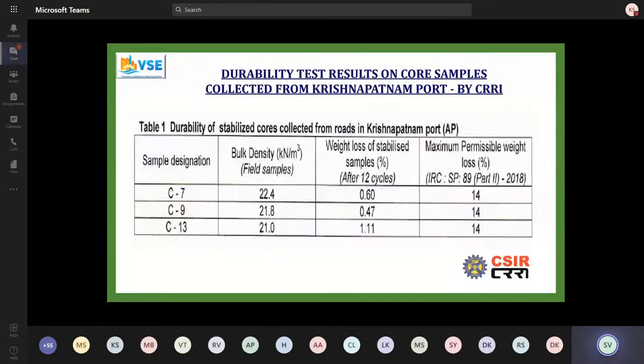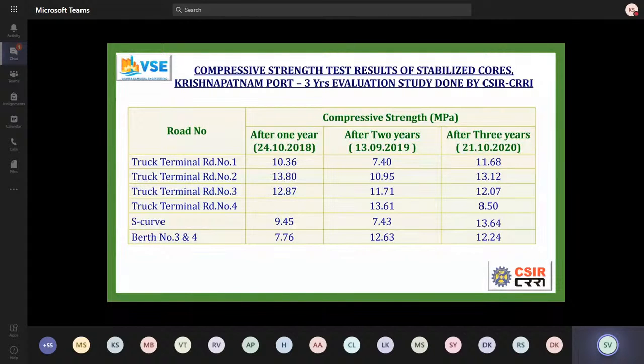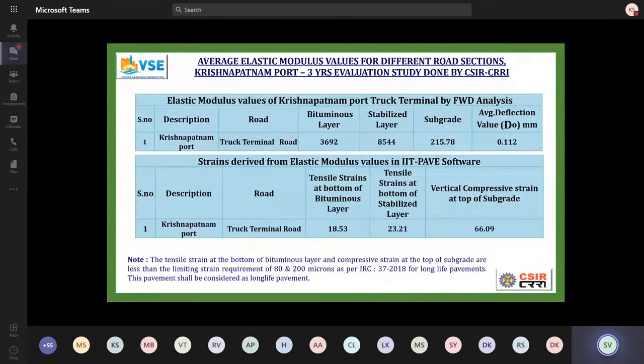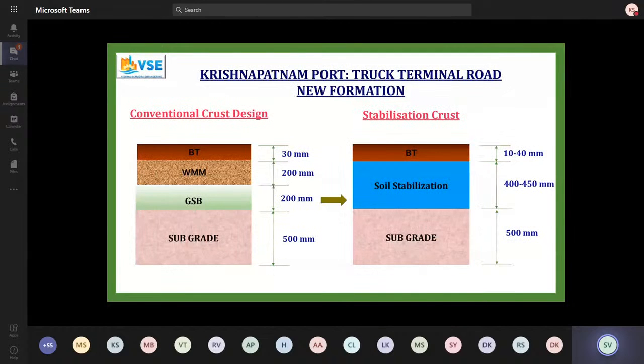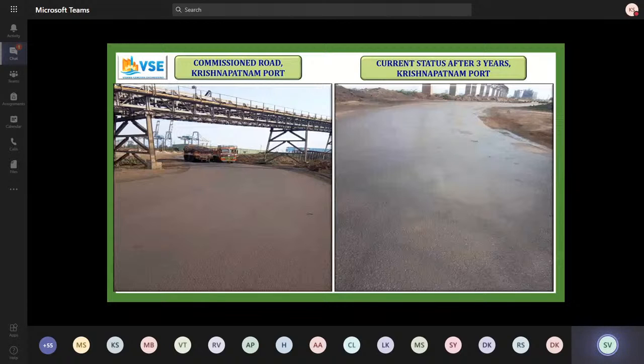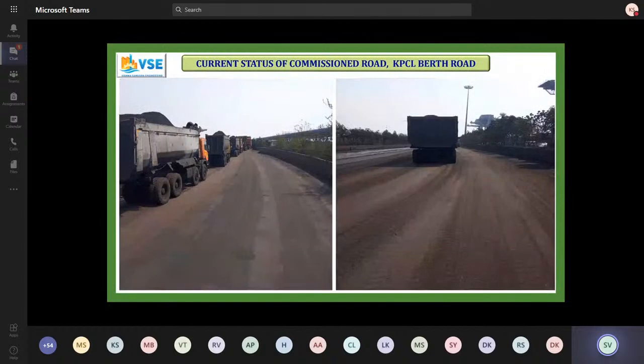This is again tested by CRRI. If you see, the absorption of water after durability is around 1%. And these are the strengths over the last 3 years. It's gone up. Again, FWD was done on this. If you see the values of deflection, the deflection is very, very minimal. These are the roads after 3 years at various locations. We've also done a test specifically on one point for the S-curve. We wanted to test if there would be any rutting or undulations because the loads are transferred when the vehicles are turning. And we found that there's absolutely no undulations or rutting. These are the kind of vehicles, like I said, on a road right next to the berth. So very heavy loads, and it's holding up very well.